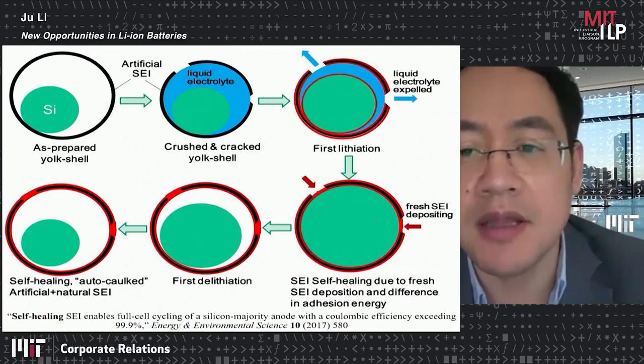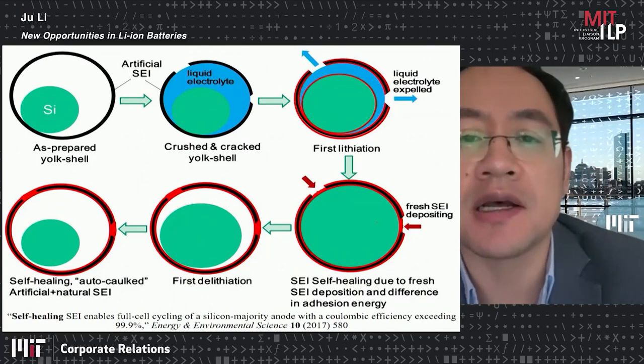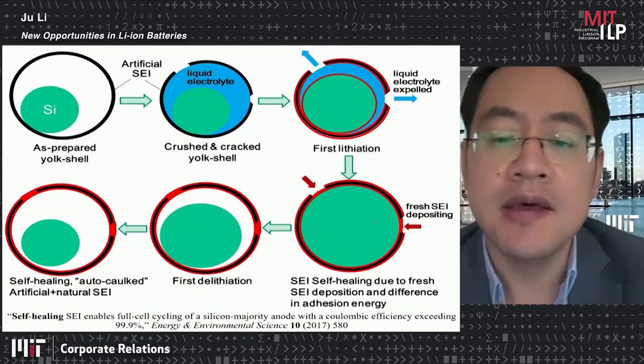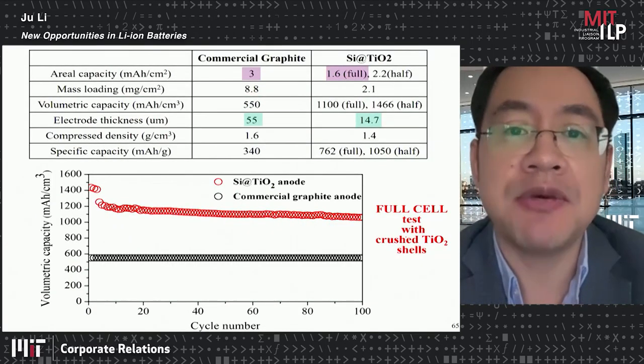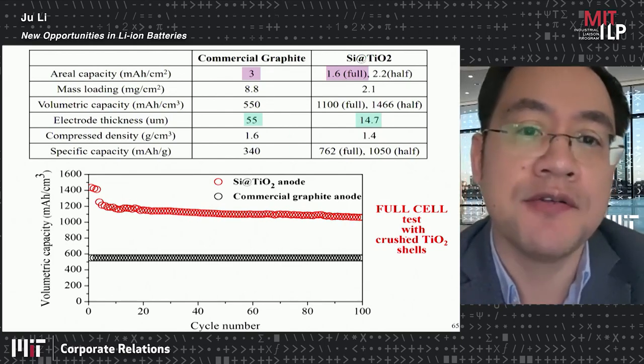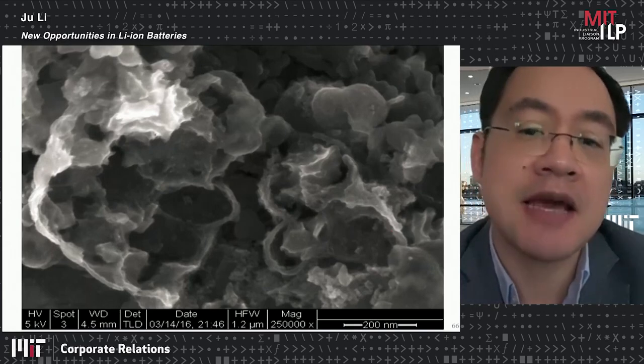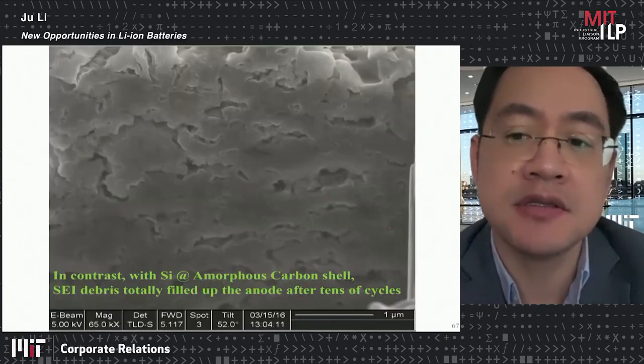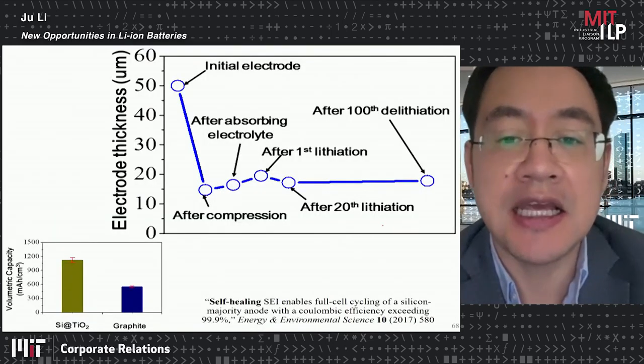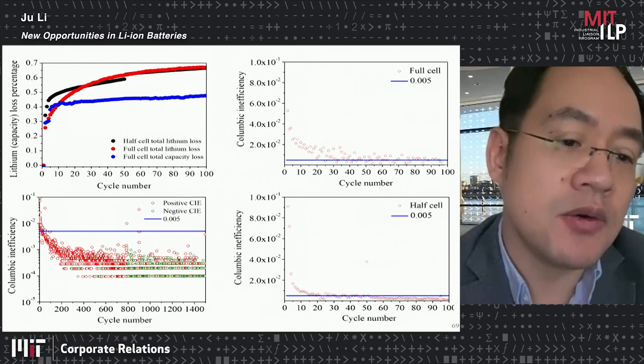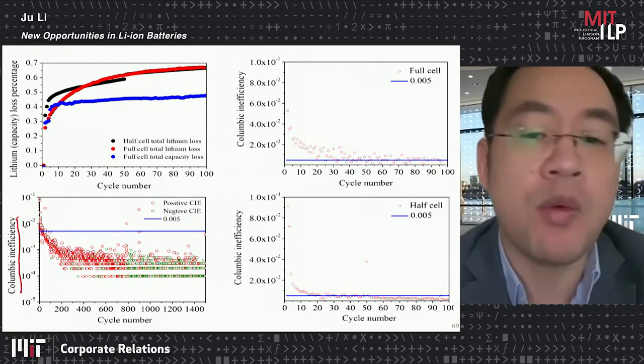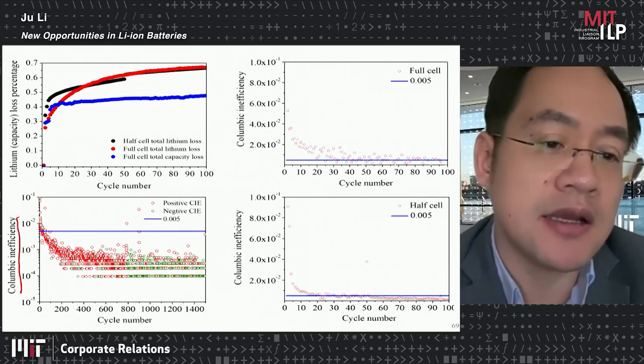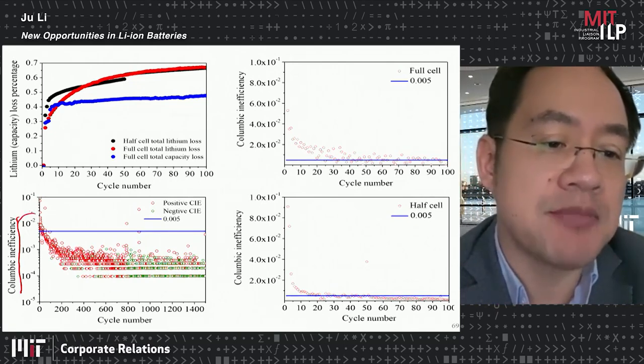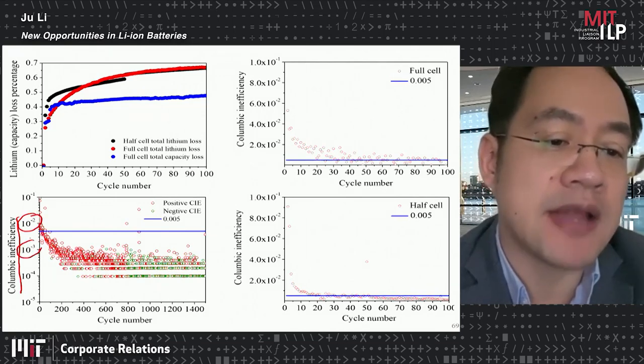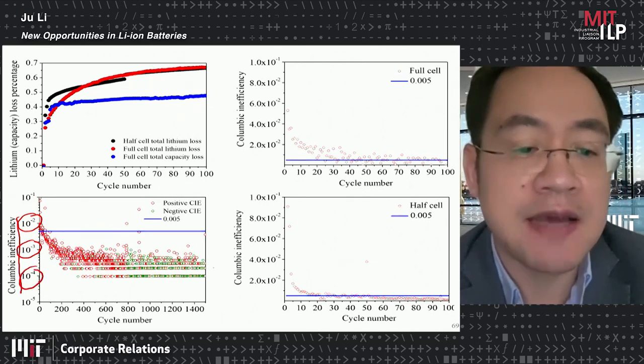But what we are curious about is, after the initial formation, after the initial cycling, can you reach a Coulombic efficiency that can be used for grid scale storage or not? Because to cycle for several thousand cycles, you need better than 99.99% Coulombic efficiency. What we found is that that's actually indeed possible. Here we're plotting the Coulombic inefficiency, which is one minus the Coulombic efficiency, in log scale. So this is 99% Coulombic efficiency. This is 99.9%. And actually we've hit the instrument resolution, which is 99.99%.